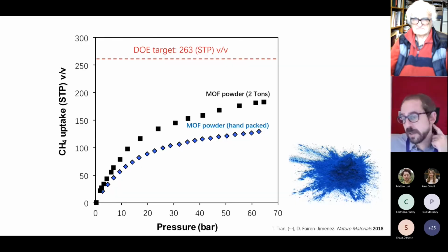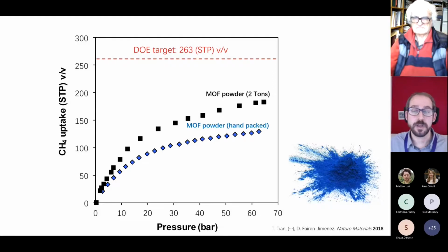They said, well, this is for the powder that you press with the hands. They tried to densify this using tons, and because they are able to increase the density of the powder, they are able to increase the volumetric capacity of the material. 2 tons is not very high. They tried 5 tons, and this is the problem that I was describing in the previous slide.